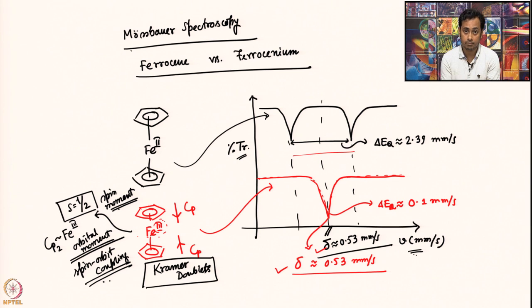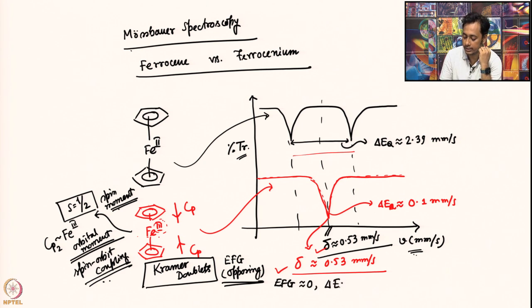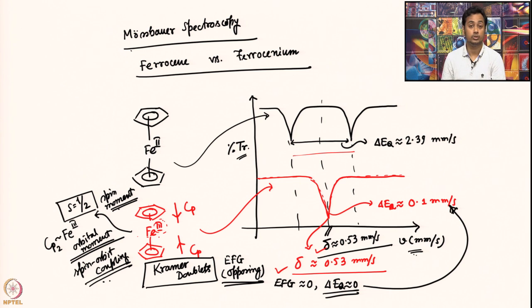These Kramers doublets ensure that you have two closely lying states, and this iron plus 3 system populates both of them. Very interestingly, either of these doublets has an electric field gradient, but they are opposing in nature. So the actual EFG that I am going to see on average is going to be close to zero, which is reflected as an almost negligible quadrupolar gradient. So quadrupolar splitting is almost zero over here. That is what we are seeing.